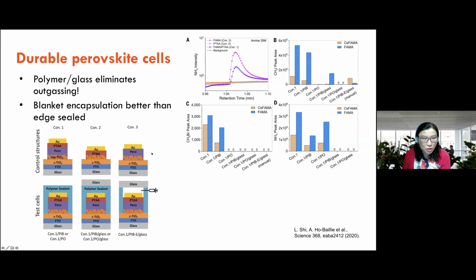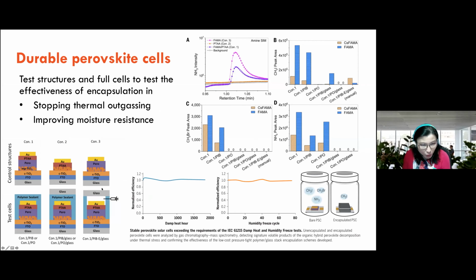So what's the conclusion? We found that the polymer-glass encapsulation does two things. One is it stops the moisture from going in. Two is there's no void. So when you use the blanket, it takes away the void, and therefore it takes away the opportunity for the perovskite to outgas, and therefore it stops the decomposition reaction from proceeding.